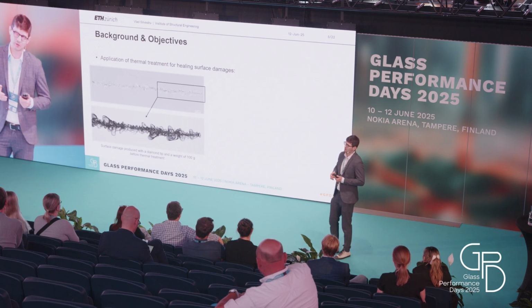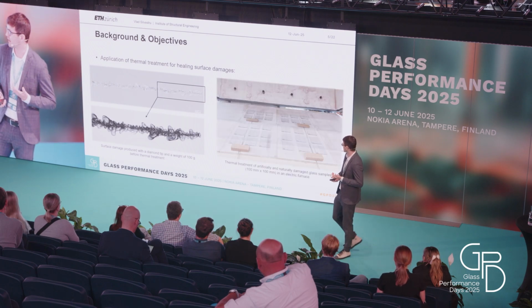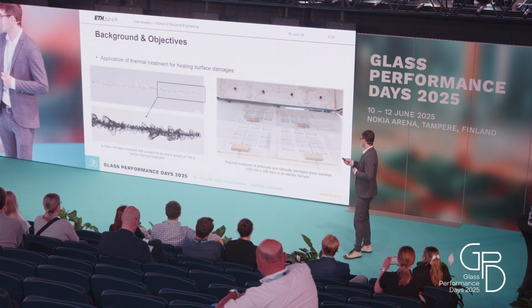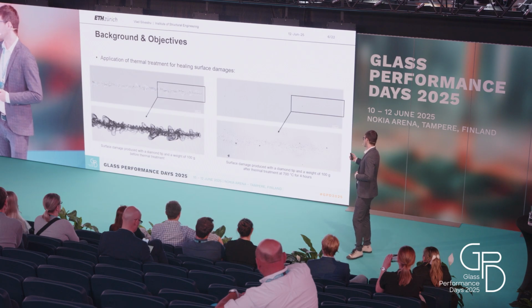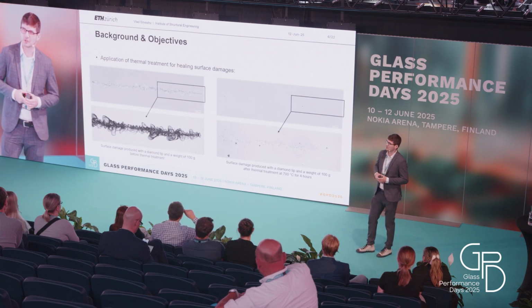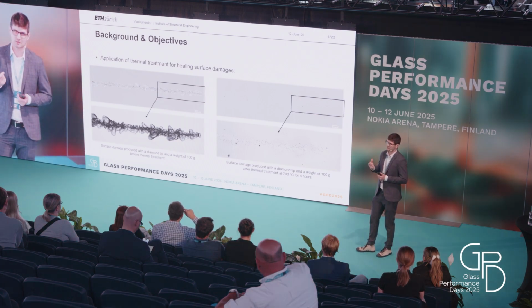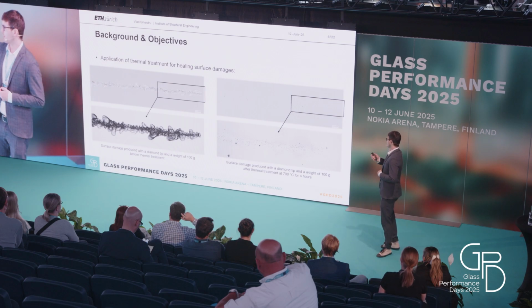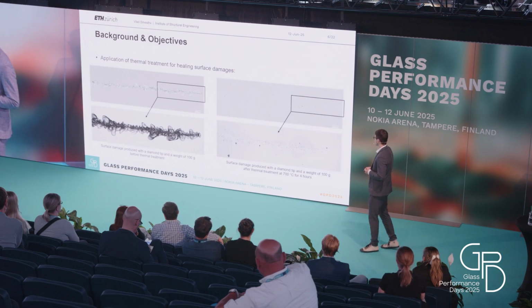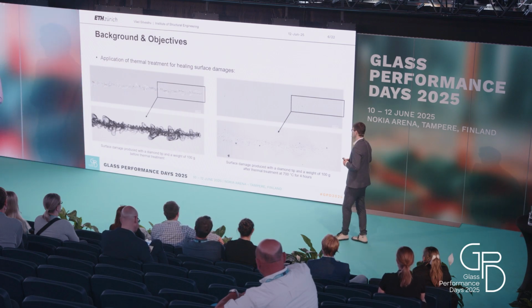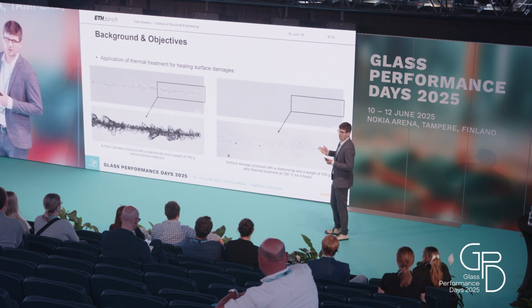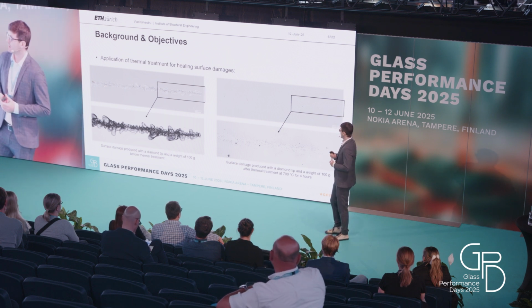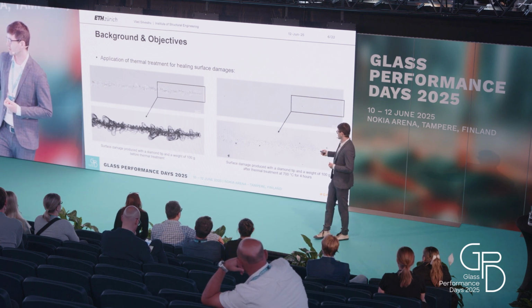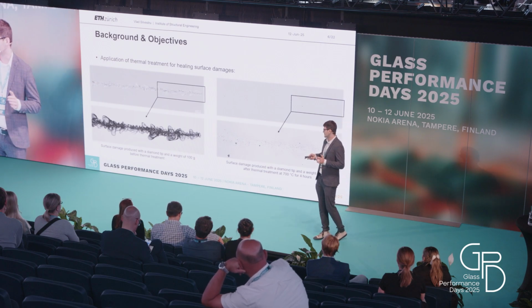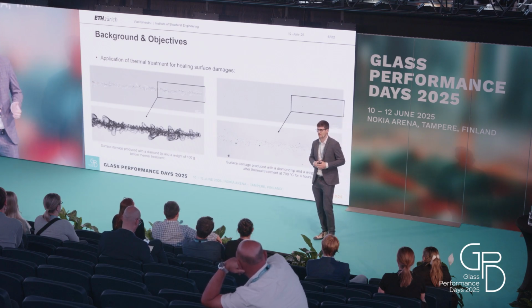So I thought, what would happen if we go higher with the temperature? I just want to show you, this is at 700 degrees, so a temperature where the glass already loses a bit of the stiffness, but the crack actually is almost healed. It was actually tough with the microscope to identify where the scratch previously was. And the strength that is achieved with this is similar to the non-scratched glass.